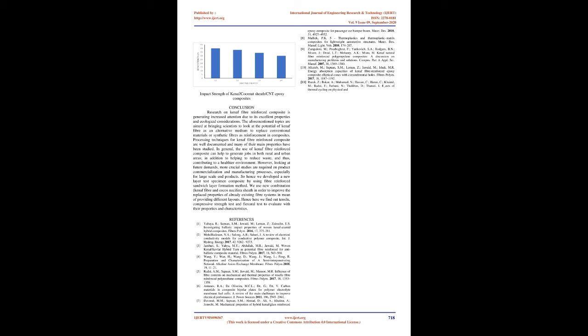Flexural properties. The flexural property is specifically important among the mechanical properties because bending induces a combination of different stresses consisting of compressive and tensile, i.e. the top layer of the hybrid composite is subjected to compression while the bottom layer is in tension. The position of the woven layers and fiber properties plays a vital role to improve the flexural properties of the laminated composites. The flexural strength and modulus of different layering sequence are shown and compared in Fig 7.3 and 7.4. Interestingly, it was found that the hybrid laminate L2 possessed the highest flexural strength, 96 MPa, and flexural modulus, 8.3 GPa, than pure Kenaf fabric, L1, reinforced epoxy composites.